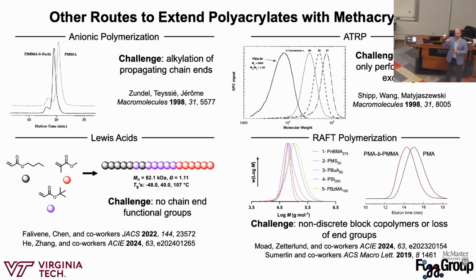They add in a little bit of comonomer on each chain extension to help overcome that equilibrium. So you add in a little bit of the next monomer to make sure that there's enough chain ends that can propagate, so the energies actually match during the reaction. And if you're trying to do a technique like lithography that relies on really precise interfaces, you're not going to get precise interfaces doing that copolymerization technique, because you're actually getting these sort of gradient copolymers.